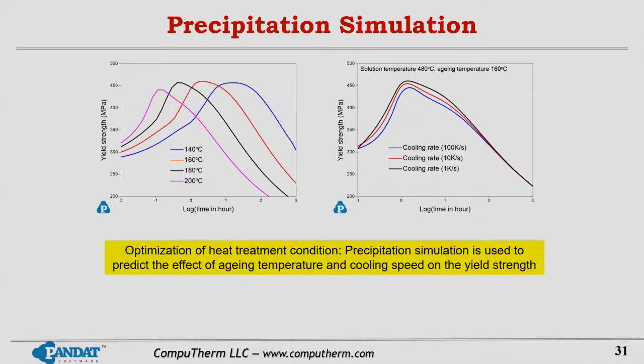So with this precipitation module, basically we can perform some virtual experiments. We try different heat treatment temperatures, different cooling rates, so we can play with it to see what's the best heat treatment condition for you to obtain the microstructure you like. This is very important to optimize the heat treatment condition.